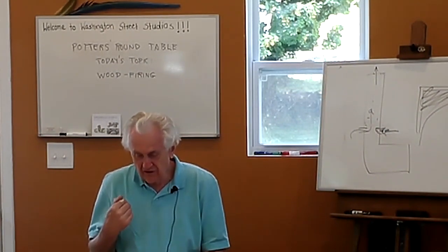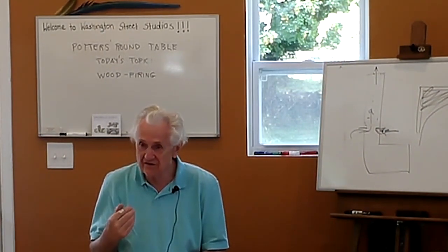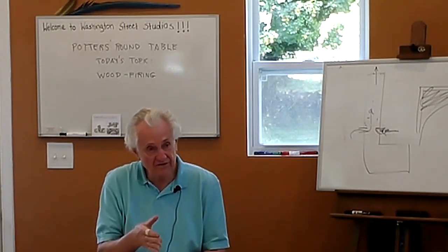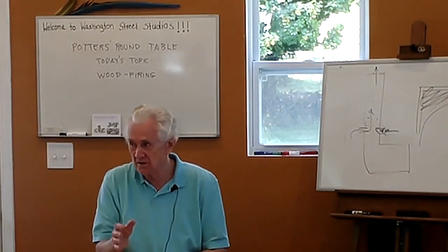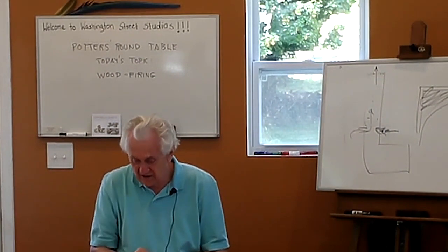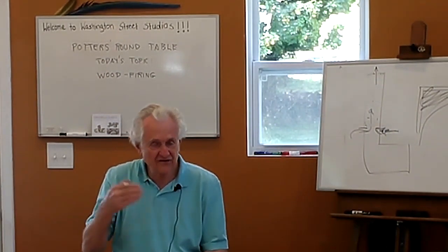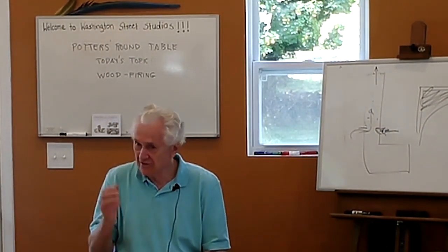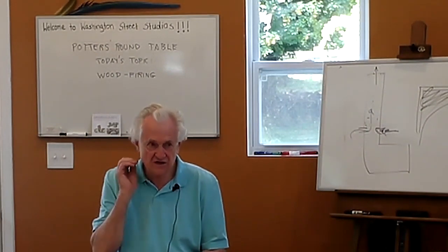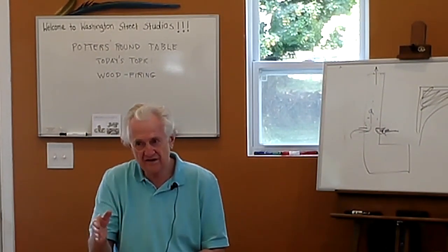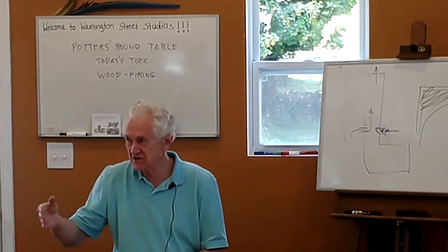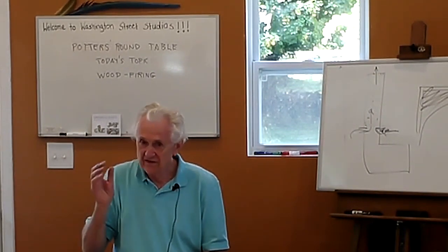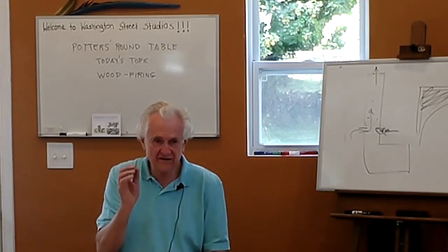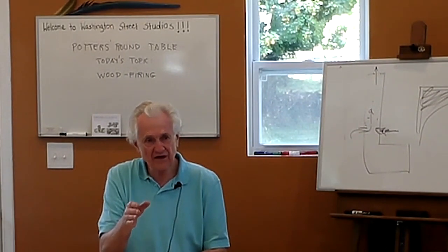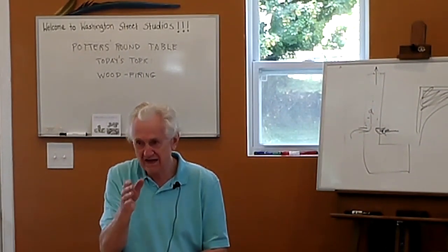the problems could be either the temperature is not hot enough so that the ash didn't get a chance to melt, so you were still accumulating ash on the pots, or the late stoking was too violent, that you're throwing in wood and you're stirring up the ash and you're creating a lot of ash too late in the firing to allow enough time for that ash to melt. Because the ash will stick, once the pots get hot, the ash will stick to it, but you have to allow enough time for that ash to melt in place.